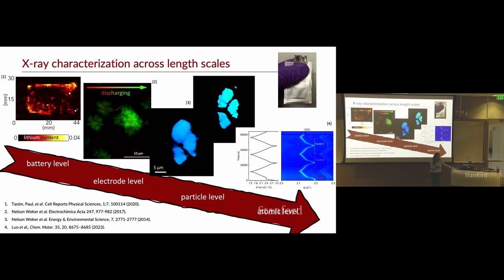But there are major problems on the anode because you have lithium metal plating onto the anode. It forms dead lithium, which means it doesn't dissolve back into the electrolyte and go to the cathode. So it becomes lost lithium metal. Ways to address that are to improve the kinetics. You can improve the kinetics by changing the electrolyte. You can also dramatically improve the kinetics of the anode by